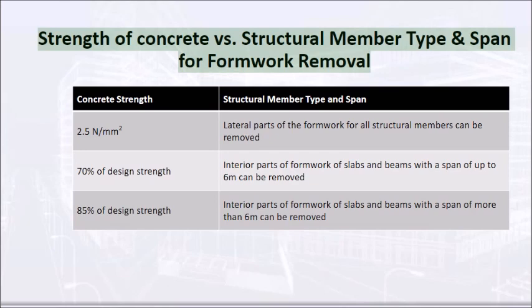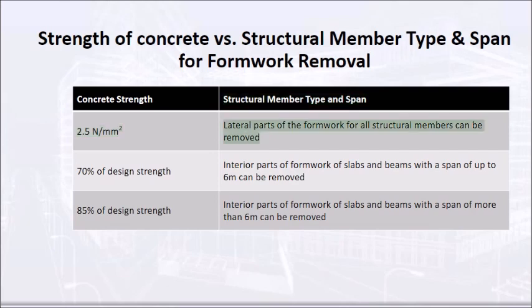Strength of concrete versus structural member type and span for formwork removal. Concrete strength 2.5 N/mm2: lateral parts of the formwork for all structural members can be removed. 70% of design strength: interior parts of formwork of slabs and beams with a span of up to 6 m can be removed. 85% of design strength: interior parts of formwork of slabs and beams with a span of more than 6 m can be removed.